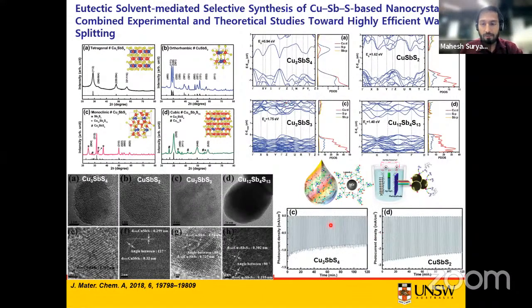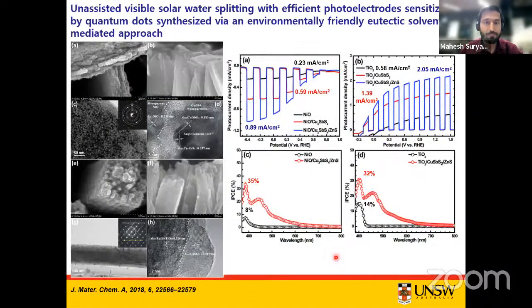We again tested these samples for their durability, and we again observed, just like in our previous experiment, that the samples are not so stable in the aqueous electrolyte, and there is a decrement in the performance after a stability test of 2 hours. And the reason again is that sulfide compounds usually corrode in aqueous electrolytes, and we need further work to stabilize these compounds in aqueous electrolyte.